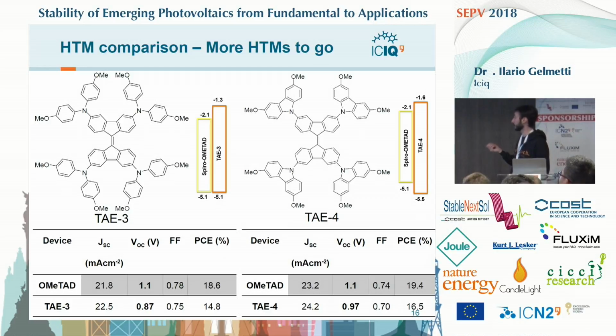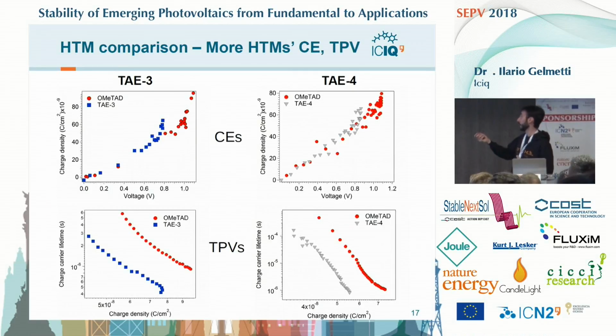Okay, so for further confirming this, we started studying other similar compounds, still from Nazario Martin's group, which in one case presented the same HOMO level, in another case a deeper HOMO level, and we still observe a lower open circuit voltage. And for what regards the photophysical studies, we still observe a shift in the exponential part to lower voltages for the novel molecules. Well, this is quite noisy anyway.